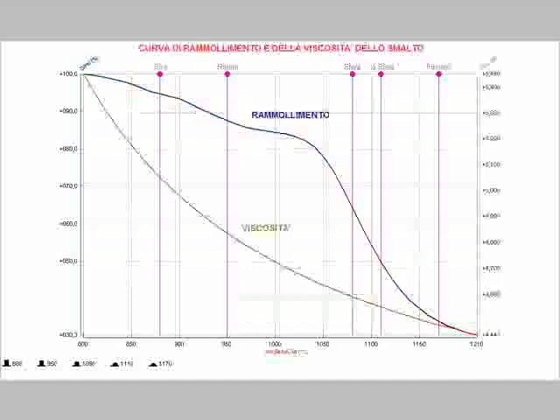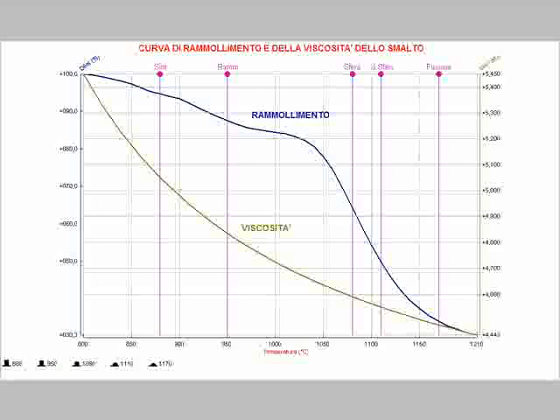The data gathered during the test can be seen as a plot. This is an example of the softening plot of a glaze. The lilac lines on the plot are the temperatures of sintering, softening, sphere, half sphere, and melting, which are identified automatically. It is also possible to extrapolate the value of the viscosity of the molten glass, using the information from the hot stage microscope and from the optical dilatometer Misura HT or LT.